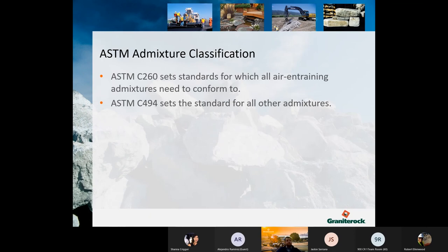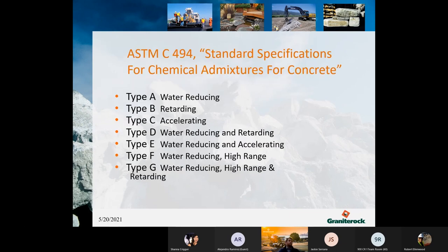There are different standards that each admixture has to meet. ASTM C260 is a standard for air entraining, and ASTM C494 for all the other admixtures. Going through the different types of C494 admixtures, there's type A through G. Type A is water reducing, type B set retarding, type C set accelerating, and type D through G are different variants of water reducing. Get into them here.